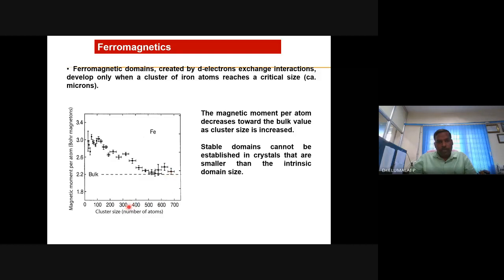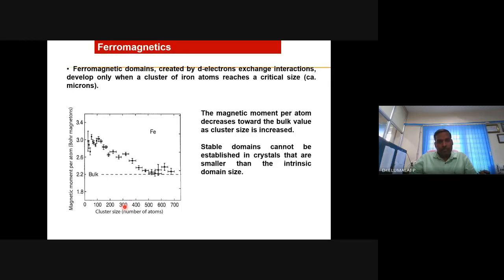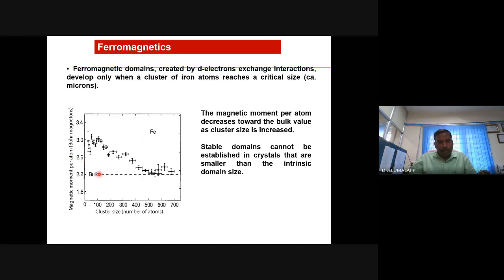Then you make clusters consisting of 300 atoms. Now you measure the magnetic momentum per atom. It is no longer that of the bulk; it is increased. Then you make the cluster size still smaller, with only 100 or fewer iron atoms. For those grains, you measure the magnetic momentum per atom. It is totally different from that of the bulk material. This is 2.2 BM and this is nearly 3 BM. In terms of percentage, it is a significant increase in the magnetic momentum per atom. I'm talking about per atom.